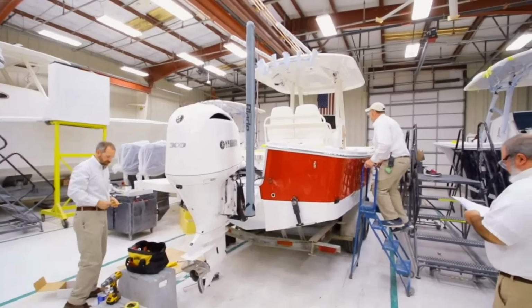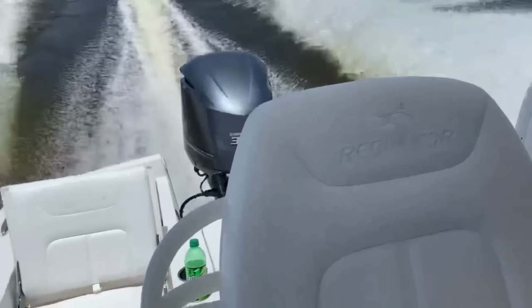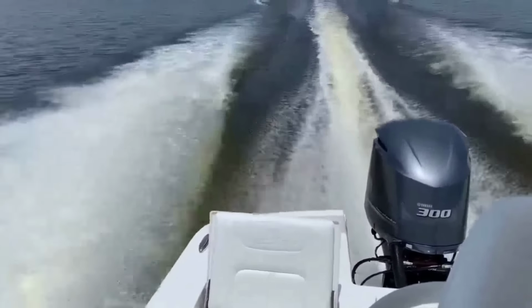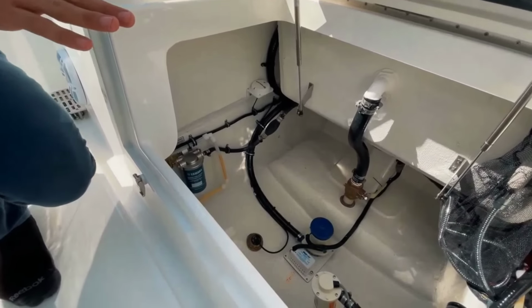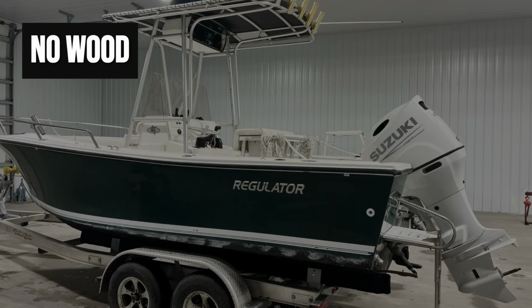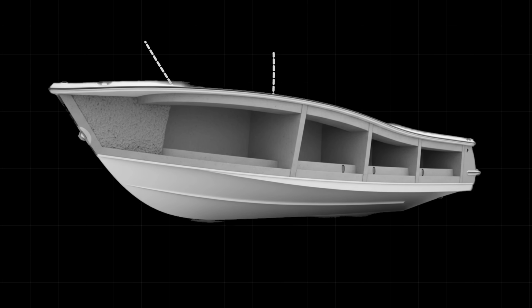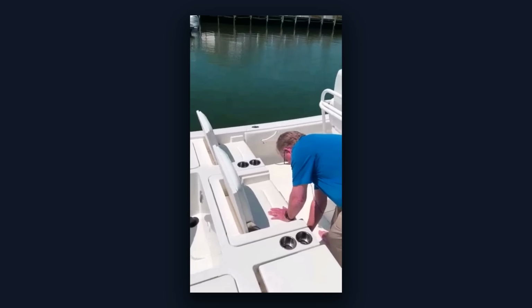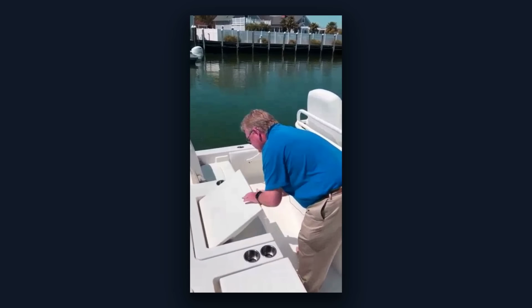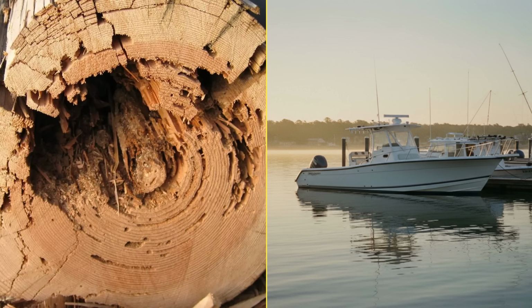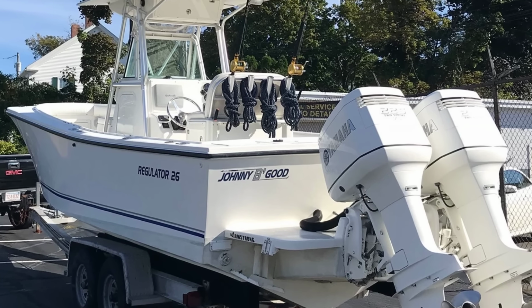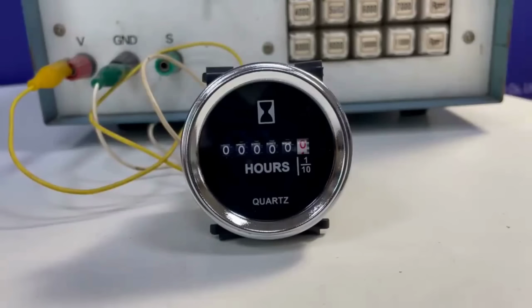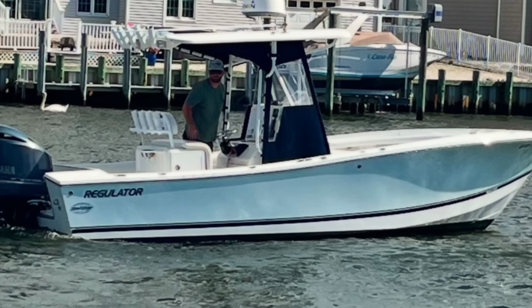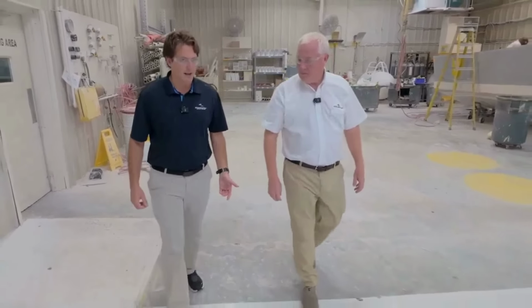The 26XO is built on Regulator's crossover platform, designed to run shallow inshore water and open offshore water in the same day. What makes it relevant to this list is not the layout versatility. It is the fact that the construction methodology that has kept 30-year-old regulators surveying clean is in this hull at the 26-foot level. A Regulator 26XO that receives normal maintenance has no identified failure mechanism. There is no wood to rot, no foam-injected void to collapse, and no mechanical transom joint to work open. The hull structure ages because the hours accumulate. It does not structurally degrade because salt water found its path in.